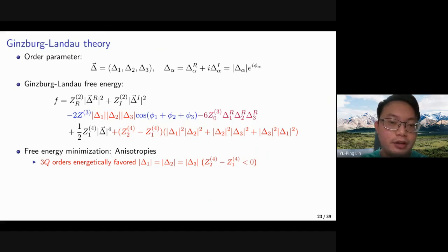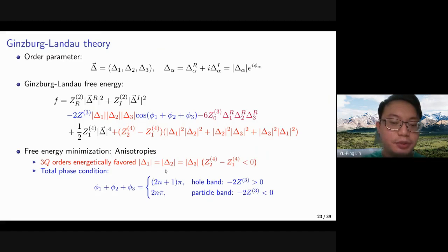And to further break the degeneracy, we could look at the blue ones. So if we look at the hole band, the prefactor here is positive. So we will want to have cosine to be -1. And this imposes a total phase condition. Meanwhile, for the particle band, the prefactor here is negative. So we want to have cosine to be +1, which imposes another total phase condition.